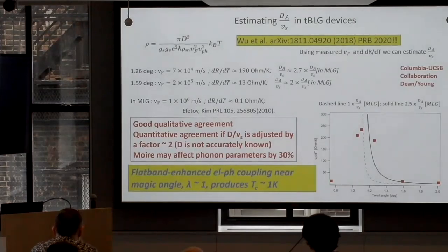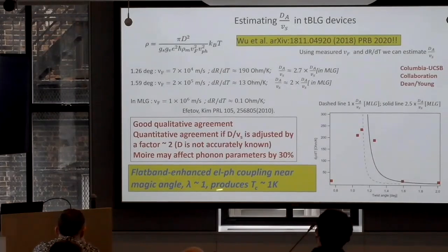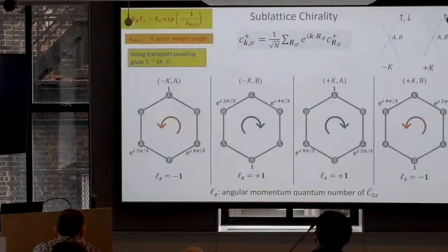So it's flat band enhanced electron-phonon coupling. And if you take the McMillan formula and put in lambda, you find lambda has now become 1. So from 0.01, it has become 100 times higher, and it goes into an exponential. So now just simple theory, which is what our original paper had, Tc is 1 K.